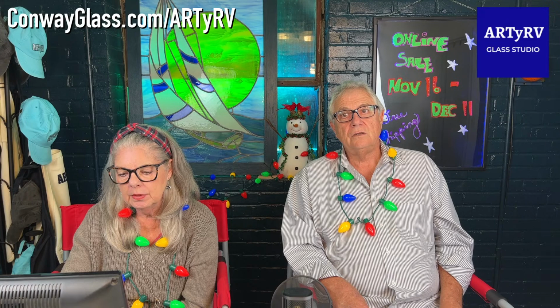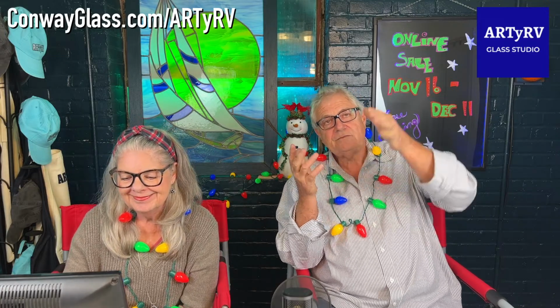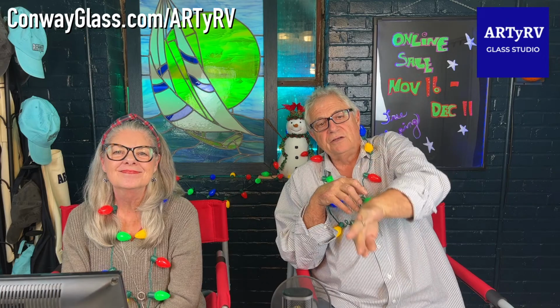Okay, here's a question from Pauline. Thanks, Pauline. What kind of cracks should we be aware of when we make a window with lead came that we should take more care in supporting? Well, a lot of times you're not just going to see cracks, but the window's actually going to start to bow and flex a little bit, and that's going to be within probably the first 4 to 10 inches from the bottom, where it starts to collapse at first. And it collapses not only from heat, but from gravity and not being supported correctly.